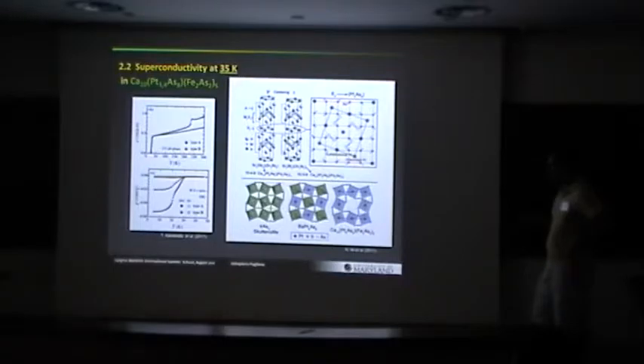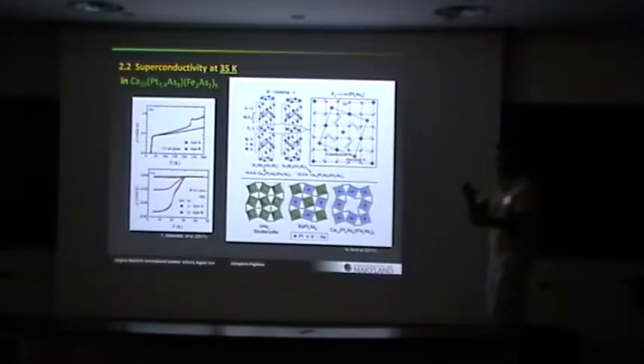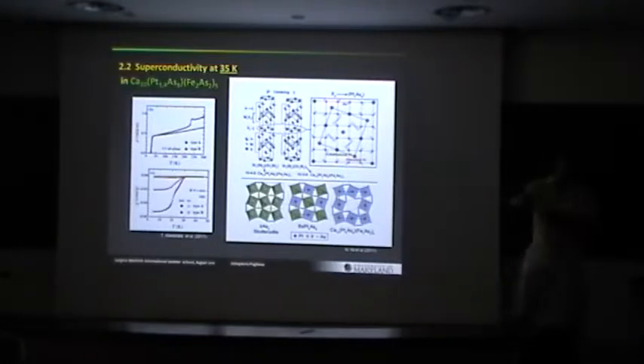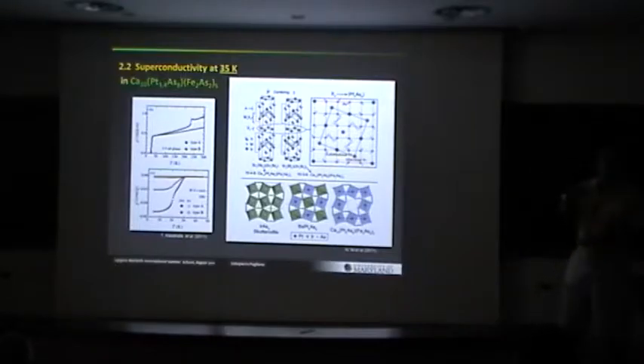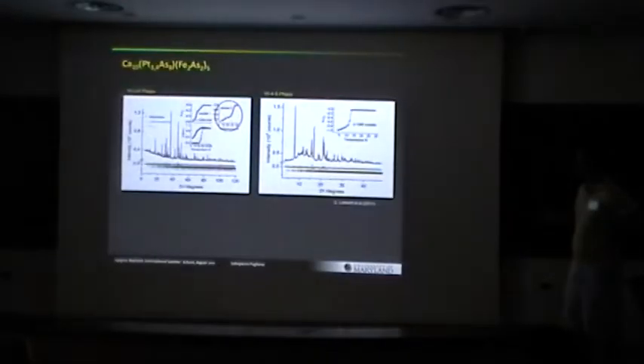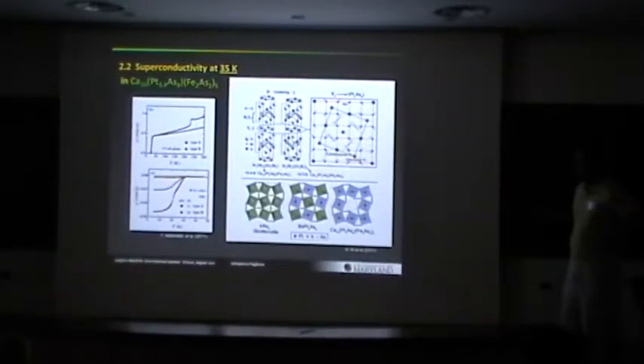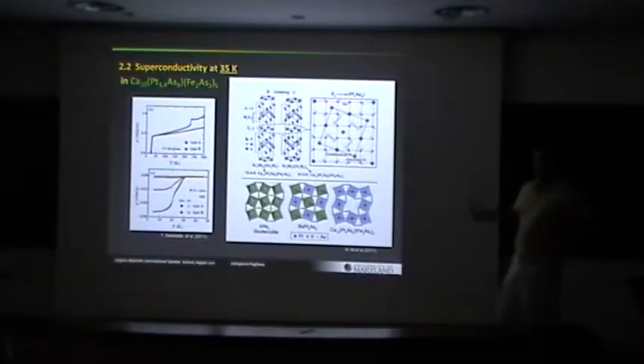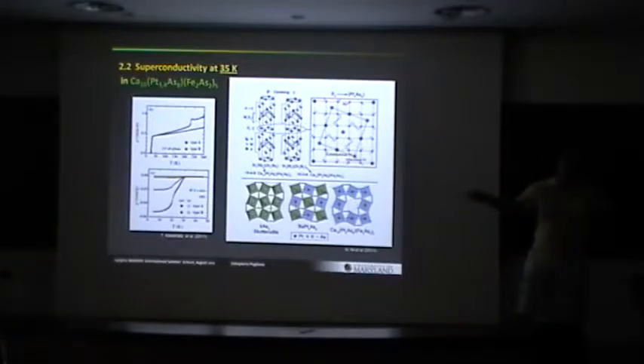Okay, and then there's some analogies to some skutterudite type intermediary layers. So you can think of this sort of as a skutterudite layer inserted into the iron arsenic tetrahedral layers. Okay. Yeah, not much data to show. Here's resistivity. This is from the Japanese group, and they claim that there's some different behavior in the two types of crystal structures. Not quite resolved yet if this is true or not. There's some weird transition here, but there's definitely superconductivity there. These guys report up to about 30K. There's an abstract that claims up to 38 Kelvin.